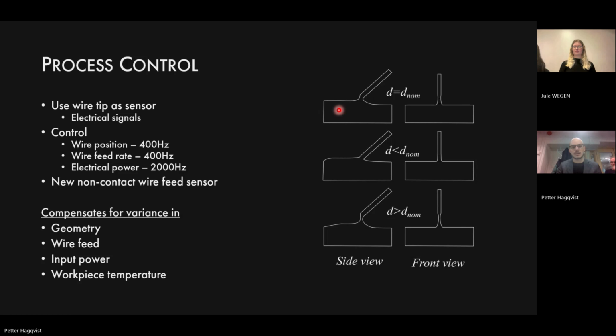In addition to this, which is our primary control system, we've also within the SESAM project developed a new non-contact wire feed sensor based on optical methods. I won't tell you much more, but it allows us to very accurately and with a very high sampling rate determine the actual wire feed rate. This has been key in order to understand some of the issues that we've faced in this project with white spots that Asun and Björn will talk about later.